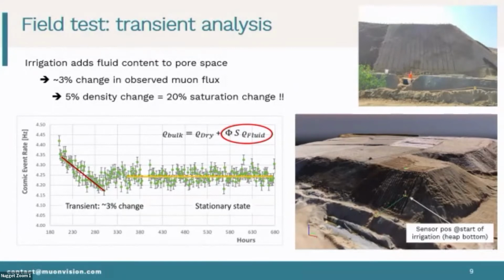And knowing the geometry of the system, we know that this means about a 5% density change in the heap. What do you expect? If you put in 20% more fluid saturation, you will see about 5%. You can get better numbers, but it's absolutely quantitative, and this all boils down to the volumetric equation. You will also notice that after this initial transient phase, there is a stationary state, which is what you expect. That's the equilibrium state of the heap, and therefore this is the equilibrium fluid content.